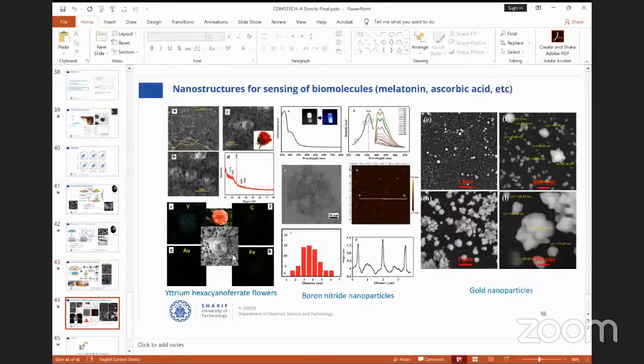Just to show some examples of what we did. For example, we used yttrium hexacyanoferrate flower nanoparticles on the surface. You see it's like a flower on the surface of three-dimensional graphene. And we used it for melatonin. We showed that melatonin, which is a factor for sleeping, can be measured very quickly and very efficiently in drugs or in pharmaceutical applications.